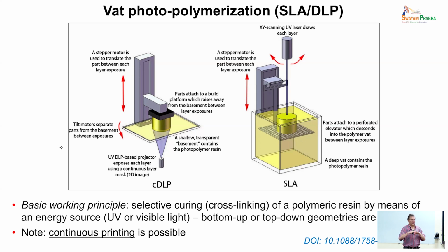DLP generates quite strong stepping effects. So you can certainly see the difference between each layer. And if you're using ceramic slurries, then you typically have issues in terms of the distribution of the powders within each layer because of settling issues. So you typically have weak interfaces that you need to consider. These technologies were, of course, developed for polymers. They are used also for metals, not DLP, because you need to have something that is transparent to the radiation. So metals will not be suitable for that, because the radiation typically is around 405 nanometers. So it's a high energy, but still in the range of the visible, and the metals, of course, absorb.